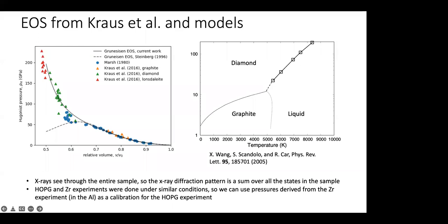But that wouldn't mean the pressure is lower, or certainly wouldn't mean the longitudinal stress is lower. If we were compressing in a more elastic-like state, that stress-strain response would be above the Hugoniot. So the nominal pressure, or stress, whatever you want to call it, would be above what it would be at equilibrium.